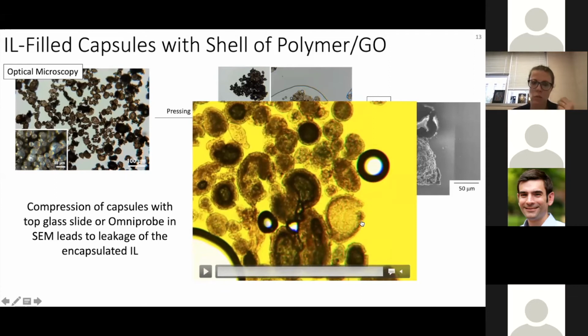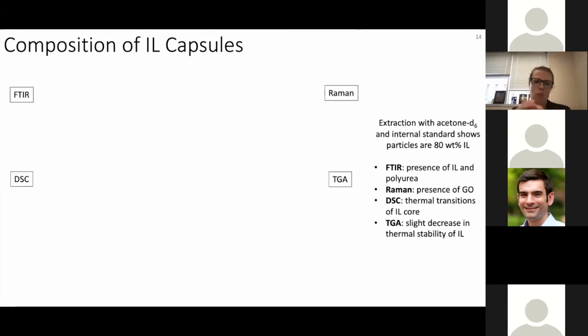So we're actually working with my colleague George Farr here to measure the mechanical properties of individual capsules, to see how much force we have to apply before we actually break the capsule shell. We can also extract the ionic liquid from the capsule shell using a solvent that the shell is permeable to. So in this case, we use deuterated acetone with mesitylene as an internal standard. And integration shows that the capsules are up to 80 wt% ionic liquid.